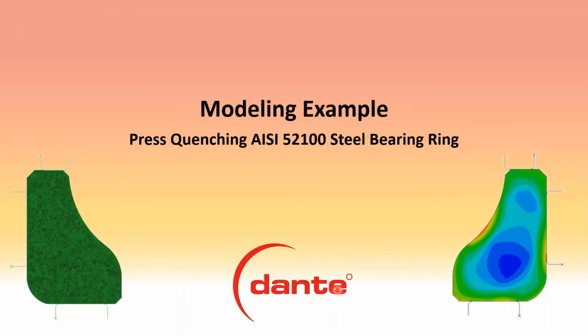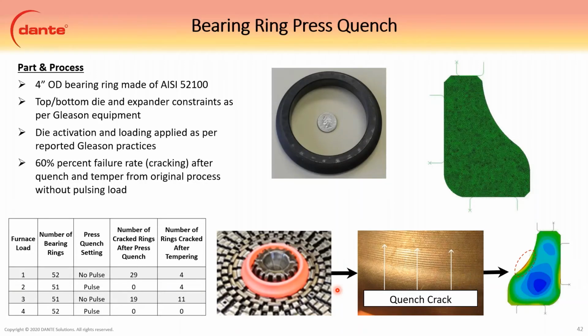All right, so press quenching of a 52-100 bearing ring. So about 4-inch OD, so about 100 millimeter OD. There's top and bottom constraints. So you can see the model on the right. So you have a top die, bottom die, and then the expander on the inner bore.